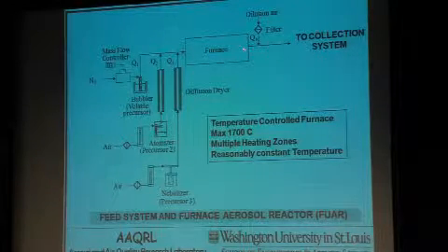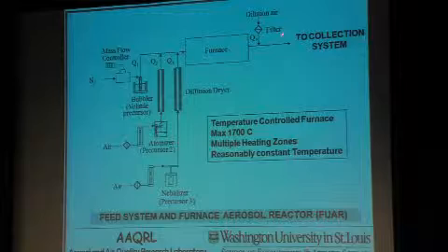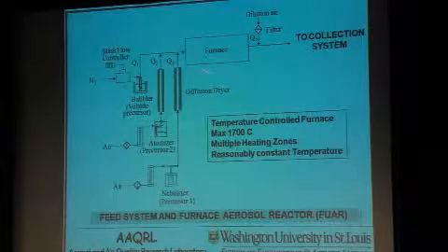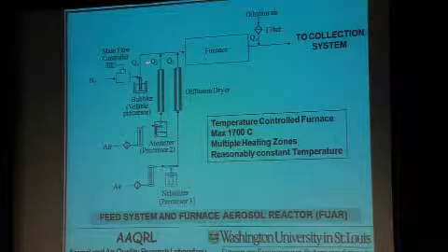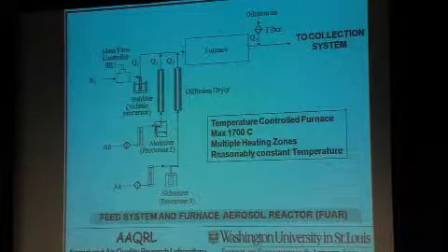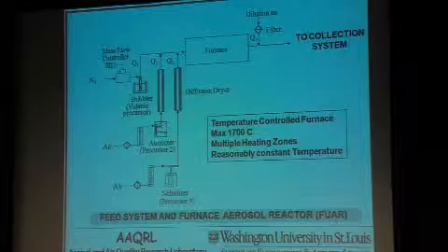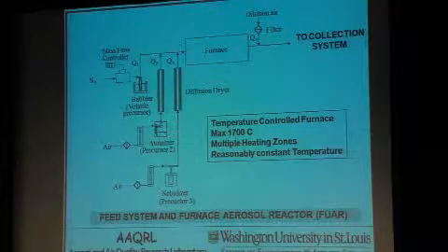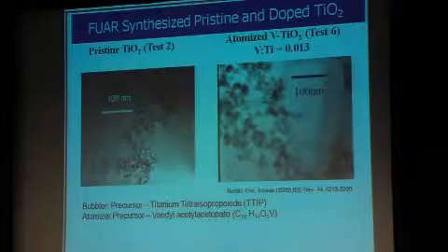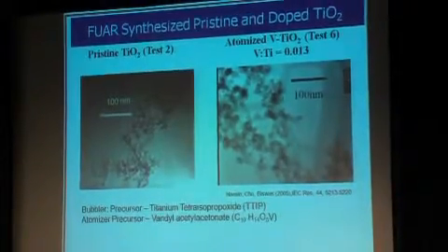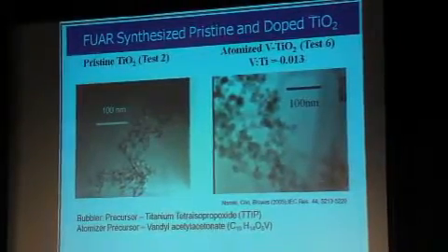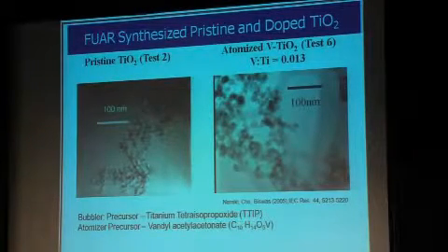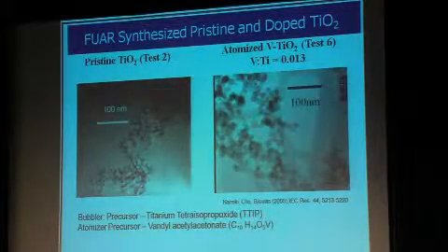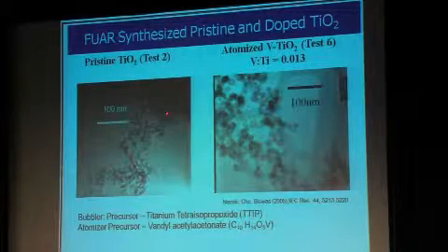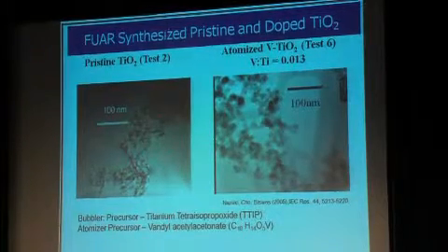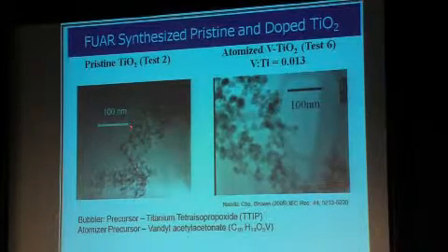And of course, eventually we want to collect the nanomaterials or nanoparticles that are produced. So this is a furnace reactor, and you can see that the flow rates and things like that have to be controlled very precisely, the temperature here, and a lot of these different precursors can be used and things like that. And just to give you an example, this is TiO2, so I can start with a titanium precursor, titanium tetraisopropoxide. It's easy to volatilize and carry it into the reactor, and you can see a nicely aggregated material that has been produced, and this is of course a 100 nanometer bar.